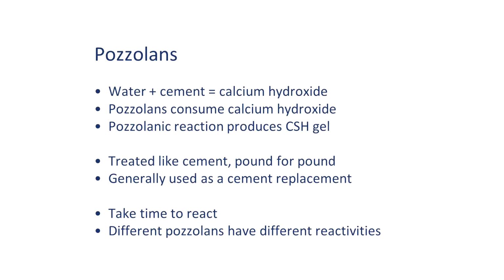So this is basically how they work. When you have water and you have Portland cement and they react, one of the byproducts I already mentioned, the calcium silicate hydrates, that's a gel, that's the desirable stuff we want. Well, there's a byproduct, it's calcium hydroxide. And calcium hydroxide isn't terrible. It's not great. It weakens the concrete a little bit, but you can still make decent concrete without dealing with it. But about 15 to 20% of your Portland cement eventually turns into calcium hydroxide. Depending on the cement formulation, it could be more, it could be less, but it's about, let's say, a fifth of your cement. That's a lot.